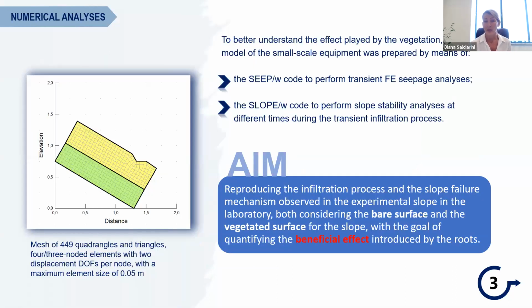So to better understand the effect played by the vegetation, we built a 2D finite element model of this small scale equipment by means of the GeoStudio suite. In particular, we used the SEEP/W code to perform transient finite element seepage analysis, and the SLOPE/W code to perform slope stability analysis at different times during the transient infiltration process, with the aim of reproducing the infiltration process and the stability mechanism observed in the experimental test in the lab, considering both the bare surface and the vegetated surface of the slope.